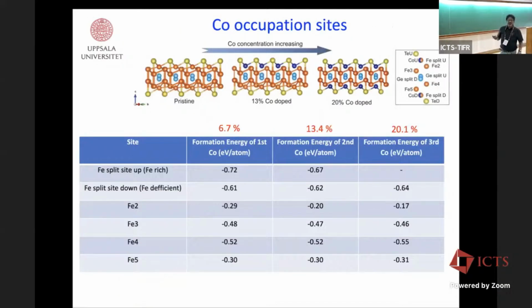And what we did, the first thing, is that we need to figure out if you dope cobalt into this system, where do these cobalt atoms go? So we figured out that the formation energy of cobalt sitting in the iron 1 up site is much lower than any other site. So in conclusion, when cobalt atoms are being doped into the system, they prefer to go to the outermost iron 1 layer. They can be in the upper layer or the down layer, but they want to occupy those sites first, and then they go to the other sites. This is the first important information.